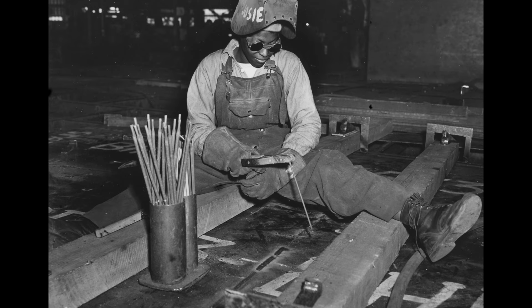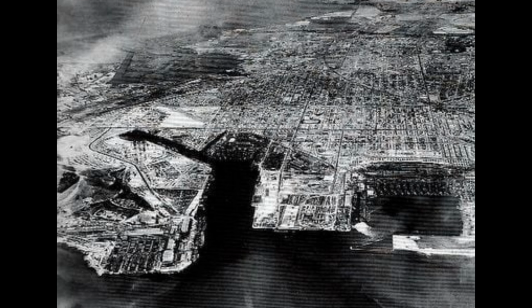The Liberty ship's squared-off design made matters worse. British naval architects had chosen hard corners to simplify cargo handling. No one realized that sharp internal angles create massive stress concentrations, multiplying normal loads to destructive levels. Each wave that flexed the hull sent pulses of stress into those corners. Combined with residual weld tension and cold brittleness, those areas became ticking fracture points, waiting for the perfect conditions to fail catastrophically.